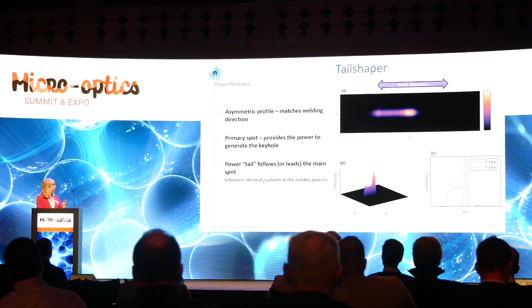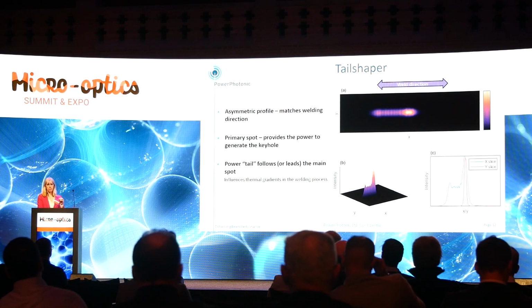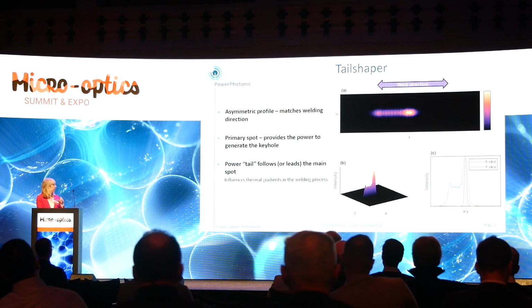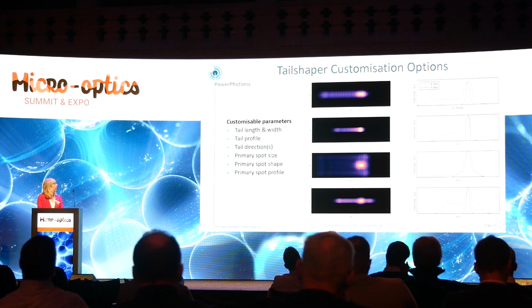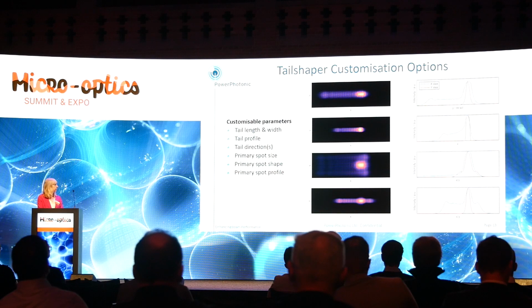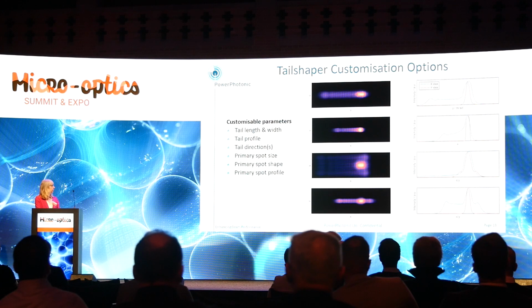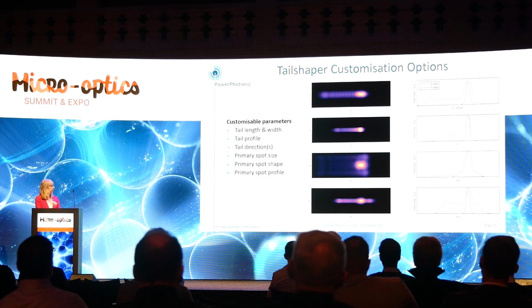The primary spot provides the power to generate the keyhole that I mentioned before, that creates the melt pool, and then the tail that follows the main spot influences the thermal gradient, so it helps with the grain direction. The tail shaper is also customizable, so you can change the length of the tail profile, the tail direction, and the primary spot size. As you can see, we've got bigger spots and smaller spots, even the spot shape, some are square, some are round, and the primary spot profile.